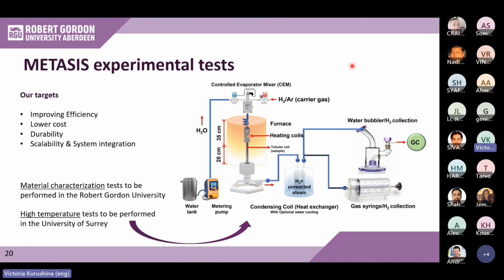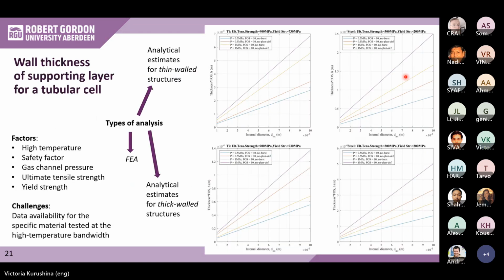So the laboratory experiments are split between the universities, and the high temperature testing here is performed by the University of Surrey. So Ajit will cover this part. And the low temperature tests are performed at the Robert Gordon University. And when designing those experiments, as I mentioned previously, in the university environment, it's important to go for the highest safety. This defines a lot the choice of the metal support for the specific tubular cell. And in this project, we are working with stainless 316 steel and titanium porous tubes used as a metal support. And already based on some analytic estimates for the thin wall and thick wall structures and a safety factor of 10, we could say that our metal supporting layer is going to be at least 1 millimeter thick. And in the project, finally, we're using about 2 millimeter thick substrate metal supports.